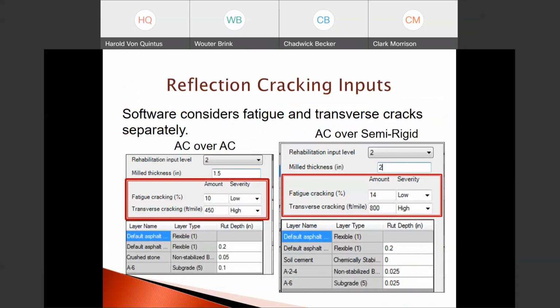Okay, now this includes some of the other inputs, and I'm going to go through these, just showing what the software considers. The one on the left is asphalt overlay over a flexible pavement, or as shown on the pavement ME screen, AC over AC. There's generally three inputs related to reflective cracking. One is the mill thickness, and then the other two, or really three, are shown in the red box, and that is fatigue cracking and transverse cracking in terms of what exists on the existing surface, or what's there and can be recorded on the existing pavement.